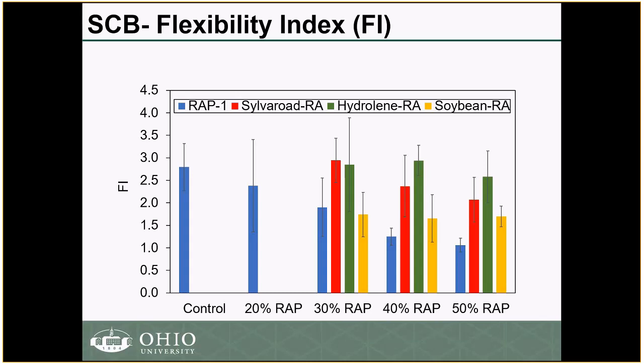What I'm showing here are the results for the 30, 40, 50 with the 3 recycling agents. What we can see is that the recycling agents were really able to improve the fatigue cracking resistance of the mixtures with 30%, 40%, and 50%. In general, they resulted in fatigue cracking resistance similar to that of the 20% and the control. We can also see that the aromatic extract, the Hydrolene in this case, had a better improvement as compared to the Sylvaroad.